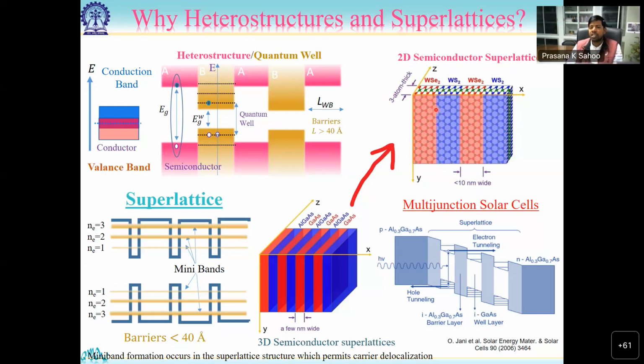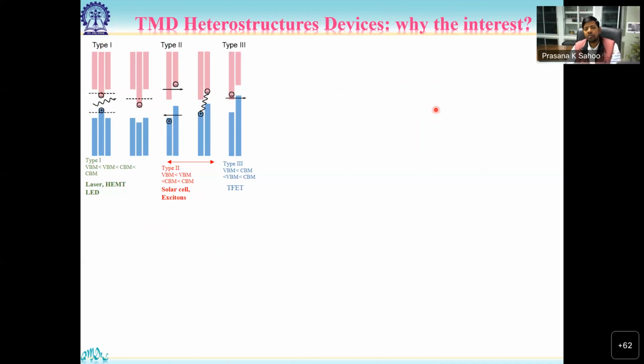Okay. This is where our expertise is. We discovered how we can make this layer-by-layer structure in lateral geometry. So if you check the heterostructures of different types, type 1, type 2, type 3, depending on the relative band alignments. If the bands are like that, with one well confined between two, it can be good for lasers, high electron mobility transistors, light emitting diodes. In this class of band alignment, it will be good for solar cells or excitons. So type 3 band alignment will be good for tunneling field effect transistors.